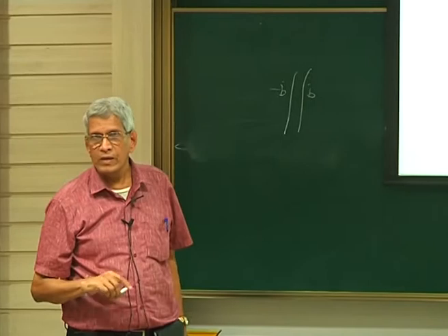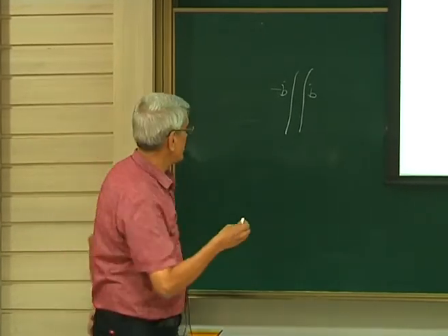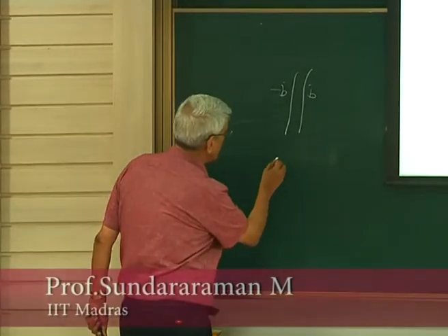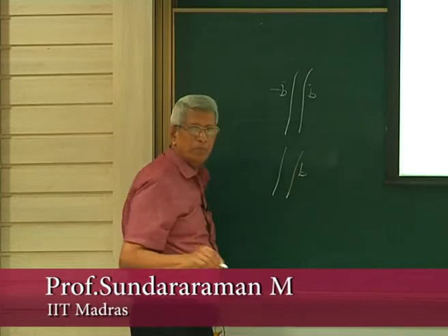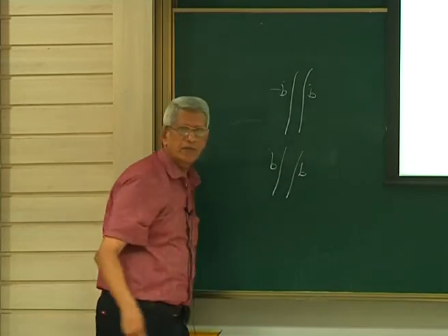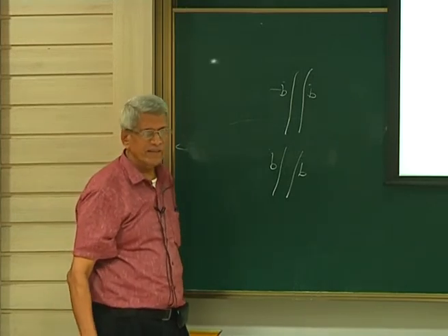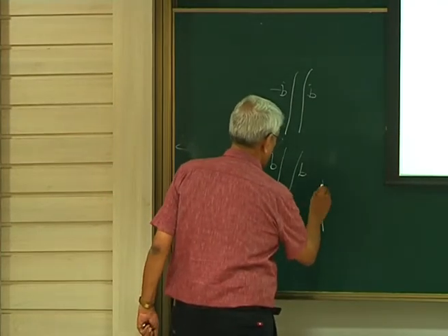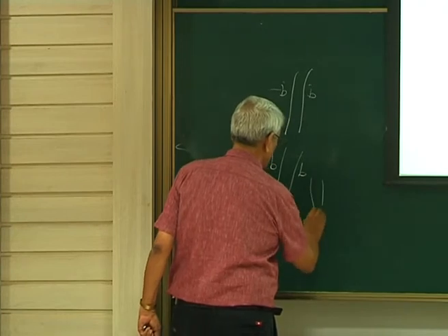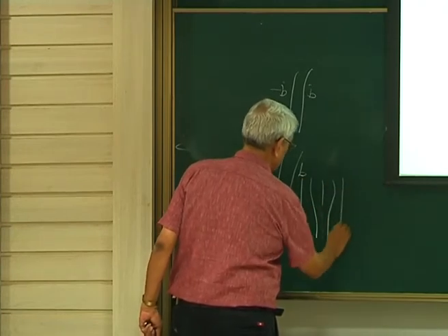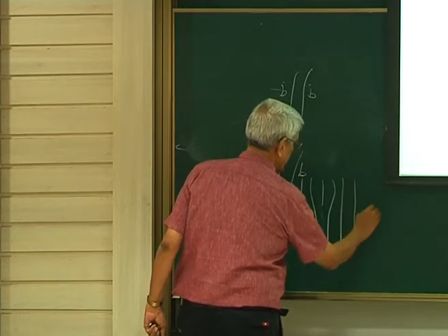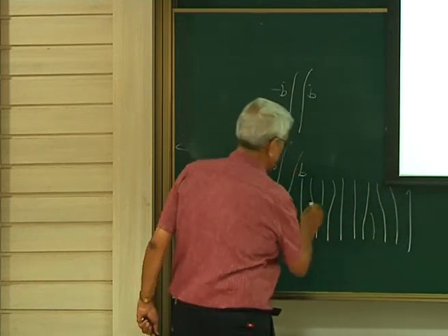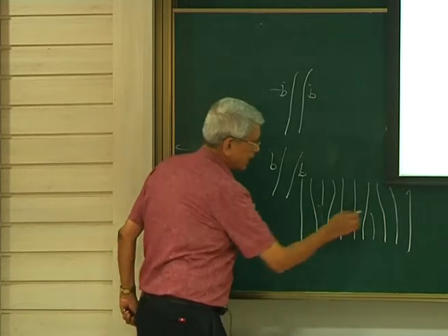Is it not? If it is not a dipole, if it is a pair of dislocations, then this will have Burgers vector B and this will also have a Burgers vector B, correct? That is right. So if these are the types of dislocations which are there, if we try to look at how these atomic planes will look, this is how it will come. This is how a dipole will look. One is B and another is minus B.